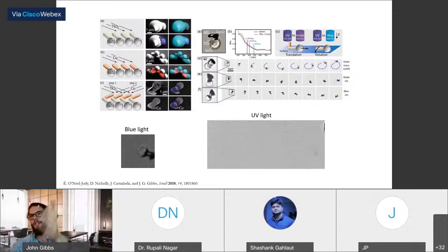So statistically, this is what happens, right? They're mostly rotational for blue, mostly translational for UV, but you do also see some rotational movement for ultraviolet. And I think this comes back to the fact that you're actually activating both of the semiconductors simultaneously when you have UV light present there. So anyway, it did work to some extent, but what we really wanted to do next is to see if we could actually take advantage of those heterojunctions.